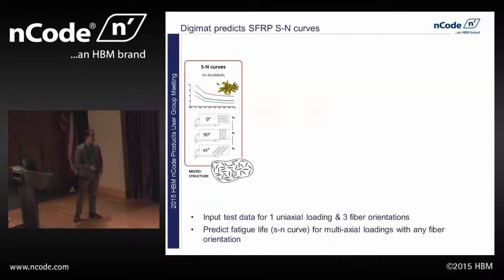So looking at generating that composite damage model, for the input we're going to need some test data at a very simplified level that we can then apply to this damage model to predict these more complex loading scenarios. So in this case, the simplified data that we're going to need is we're going to injection mold a plate, and we're going to cut some dumbbells from that plate relative to the direction of flow. And I think they touched on this in the previous presentation as one methodology for testing these materials. And one thing that he said in that is that this was a simplified approach because they were assuming that all of the fibers are aligned in the direction of flow.